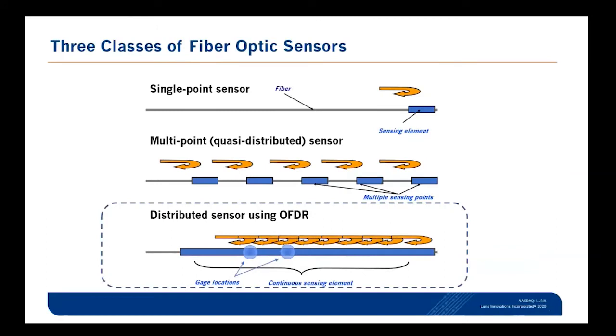So when we look at fiber optic sensing, and really sensing in general, it can be put into effectively three bins. You've got single point cases where you've got a channel that has a sensing element at the end of it. In our case, we talk about fiber. So for this, we have a Fabry-Perot element at the end, and every channel is to provide you one measurement. When you go into multi-point or quasi-distributed, in this case, you can put multiple sensors on a single channel. So for the case of, say, a Hyperion, where we're using fiber Bragg gratings, we can put 40 gratings or so along a fiber, spaced at whatever happens to be the most optimal for our test article, and it provides a single independent measurement at each one of those points on that channel.